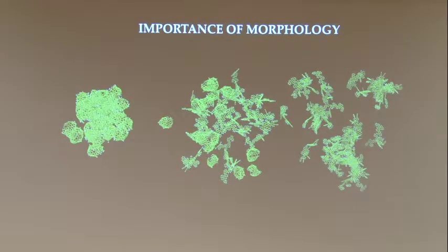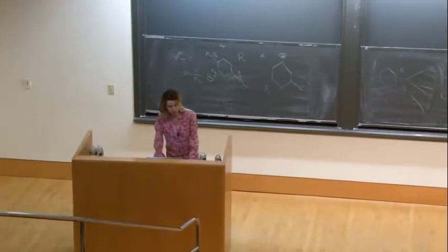This is just an example, but it shows you that on the left, if your nanoparticles are all kind of round shaped, like a ball, they really form clusters. If they are more flaky or flat, they have more problems getting together, and they form subclusters. So this speaks to the entropic contribution, not only the attraction, the enthalpic ones. And if you have a mixture, like 50 and 50, for example, of them, you have a different behavior again. So morphology plays a role.